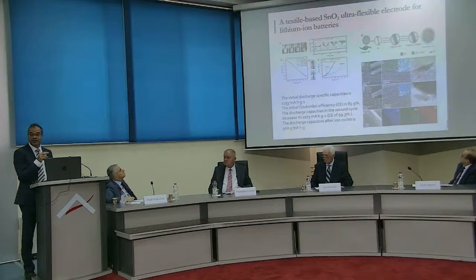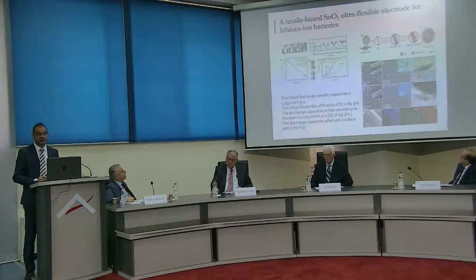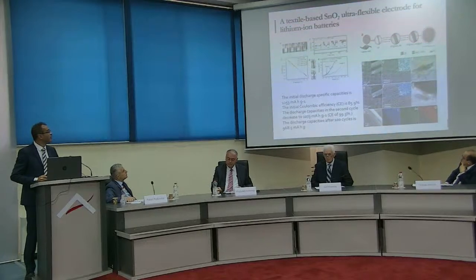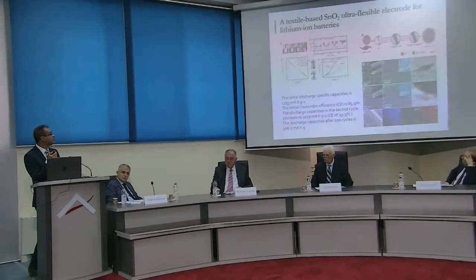Lots of you are chemists, so most of this cotton textile has OH groups and some functional groups on the surface, and it really linked well, or reacted chemically, and formed some covalent bond with the tin oxides that we are forming, basically one single compound between the textile and the active material, which makes it highly performing. The adhesion between them is quite high, which allows stability electrochemically and chemically as well. That's some of the examples we work on.